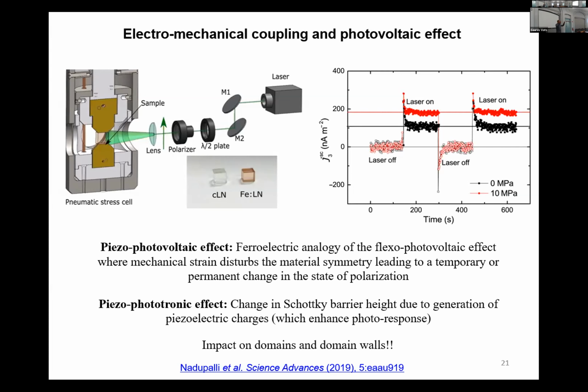So they suggested that when you apply this mechanical stress, the strain disturbs the symmetry, which leads to this excess photocurrent. It should not be confused with the piezo phototronic effect, where, in principle, when you apply mechanical stress, charges are generated because of the piezoelectric effect, and they help in enhancing the photocurrent. So they are slightly different. You could say one is a subcategory of the other, but probably not many reports, or maybe no report, on impact on domains and domain walls. So what I did is I decided to study the domains and domain walls in my material, KBNNO, with mechanical stress.